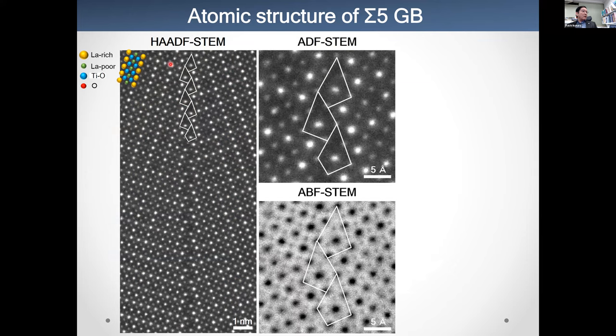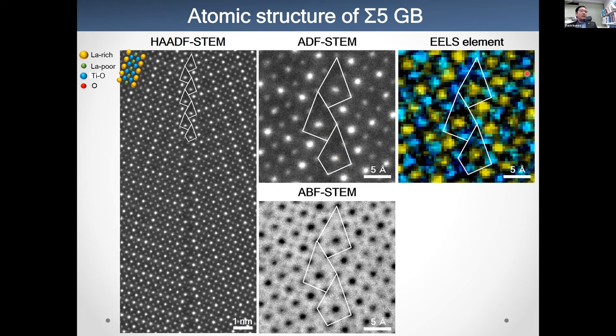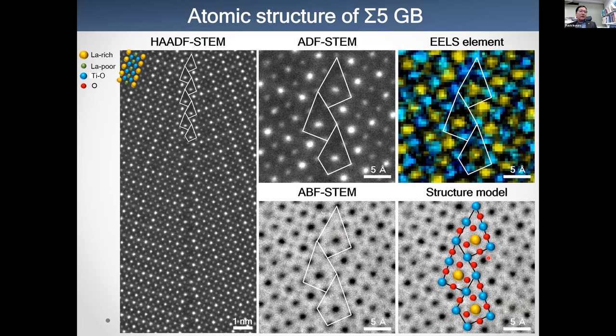This is a magnified image of the grain boundary structures, a HAADF image, heavy-element image. You can see the bright spot is always at the center of the structure unit. This is a chemical map, an atomic resolution chemical map. In the center, we can determine this is lanthanum. And at the corner of this structure unit, this is titanium columns like that. And in addition, if you look at the ABF image, you can see very thin column contrast. This corresponds to oxygen.